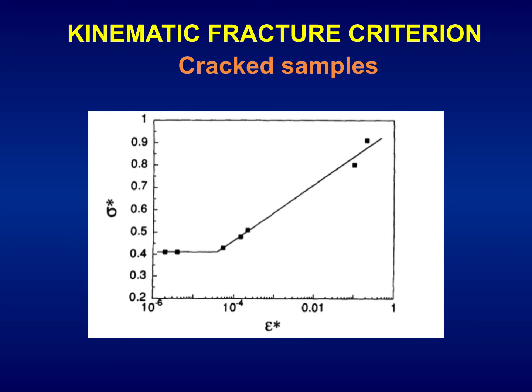in dimensionless form using the depth of the hydrogen-assisted microdamage region, the TTS depth, and the extension of this area. With regard to the dimensionless strain, it is computed as the space and time average of the instantaneous value of the crack tip strain rate. This instantaneous crack tip strain rate is averaged over the hydrogen-assisted microdamage region, the so-called tearing topography surface, and also averaged in time from 0 to the time to failure in the hydrogen-assisted cracking test. We again have an increasing trend, and to check the validity of this approach, these results with a single curve are compared with results from notched samples of the same kind of steel.